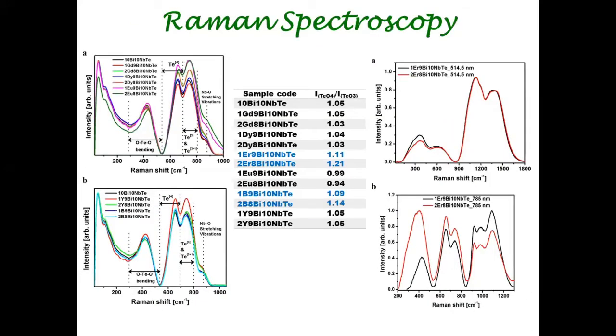Raman spectroscopy, I've already discussed some of the patterns. These are the Raman bands. In this diagram, the Raman bands around 650 and 750 are due to the vibrational modes of tellurium oxygen bonds, whereas these bands from 900 to about 1300 centimeter inverse are the photoluminescence peaks of erbium ions. These are not the Raman bands.